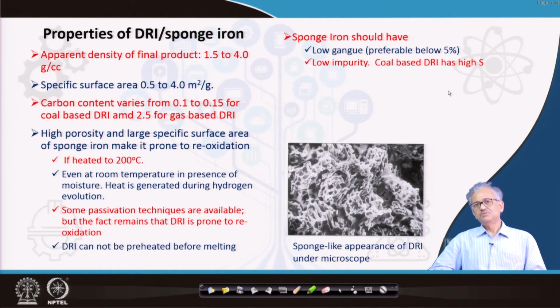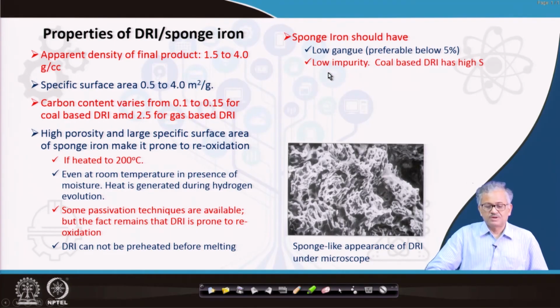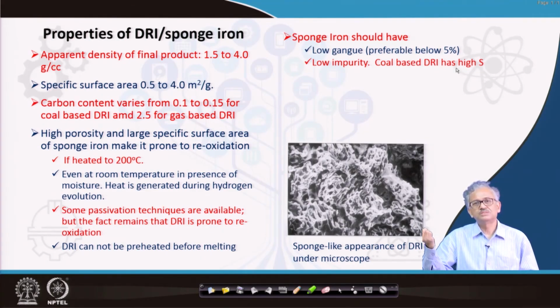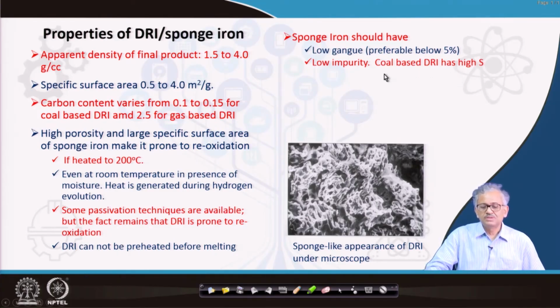So, the impurity becomes less, unlike hot metal where impurity is very high, because in liquid state impurity can penetrate much faster, while in the solid state it is less. That is why the carbon is very low, in coal based you can see 0.1 to 0.15, and also other impurities. But the sulfur can be high. Sulfur of 0.025 to 0.06 is also considered very high sulfur. The coal based DRI contains a lot of sulfur because non-coking coal contains a lot of sulfur. If the sulfur cannot penetrate inside, it gets attached to the DRI, and when you are melting, the sulfur easily penetrates. So, coal based DRI has very high sulfur.